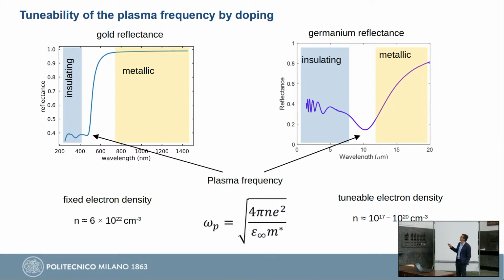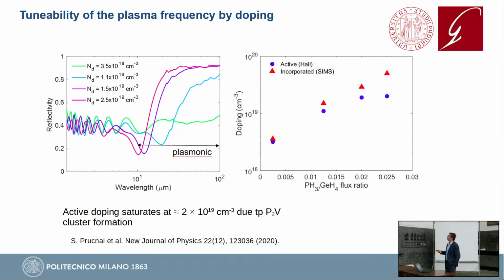So this is the case of germanium with a relatively low doping. We see again the metallic behavior. Now you see the scale is completely different. These are microns. We see the insulating behavior. The trace has these interference fringes that you typically have in transparent media. And again, we have this plasma frequency. But now this number, n, can be tuned because in semiconductors, we can tune the doping level. So we can go from 10^17 to 10^20. And so adapt my material to the purpose I want to achieve, which is sensing in the mid-infrared. So this is what we did.